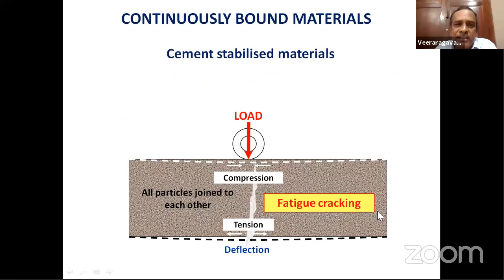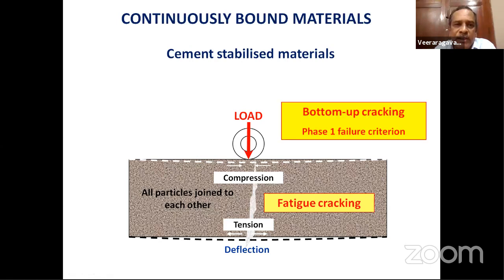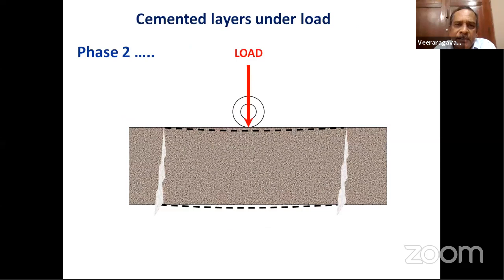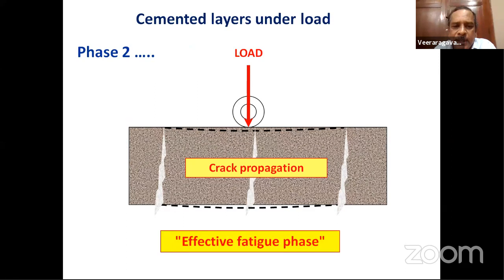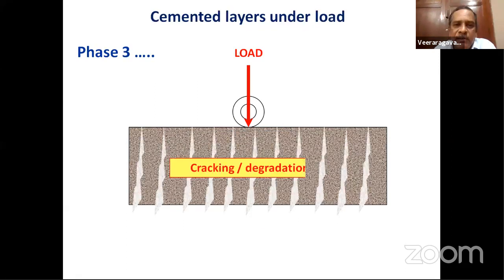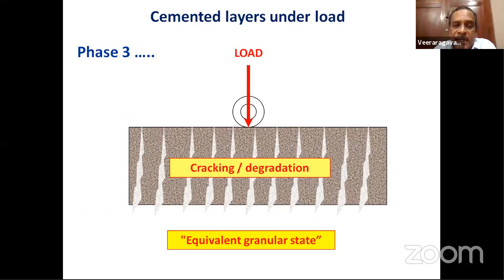What happens when you have a cement stabilized layer is that under repeated applications of the load, there will be tension at the bottom of the stabilized, bound layer. With the repeated loads, this is likely to crack. Initially, the crack will be like this, which is the bottom-up crack, phase one. With repeated applications of the load, the number of cracks will increase from 1 to 3, which is the effective fatigue phase. And eventually, the crack will propagate more and more, and the modulus of that layer will be equivalent to that of a granular state.